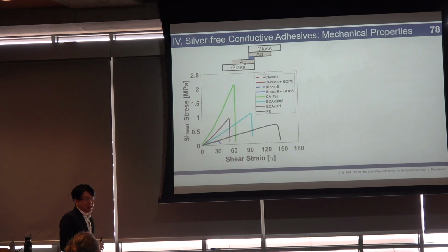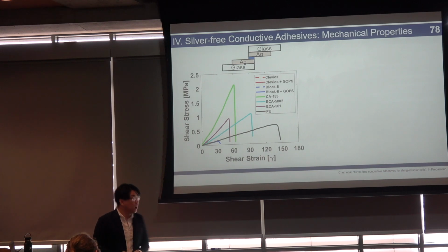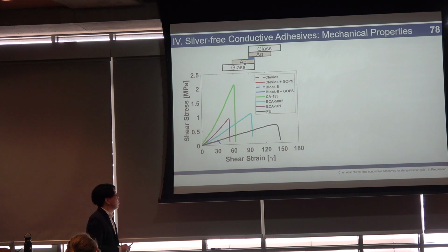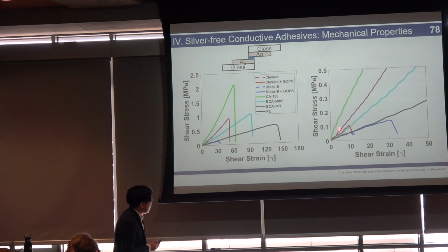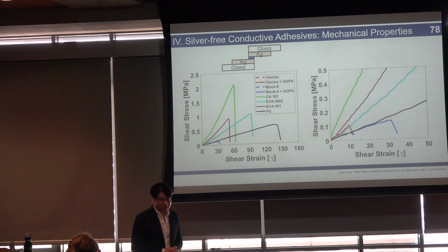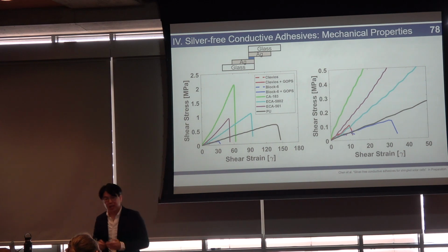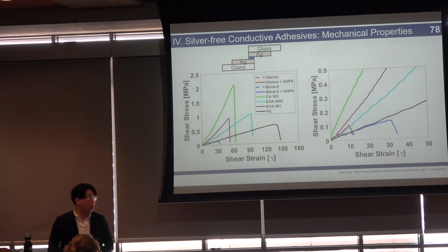The problem we are running into is the mechanical performance. The adhesion is relatively poor. You can see in all these colorful colors, these are commercial standards that we're comparing against. And PEDOT-based materials are down here, which unfortunately means that the adhesion is pretty poor.